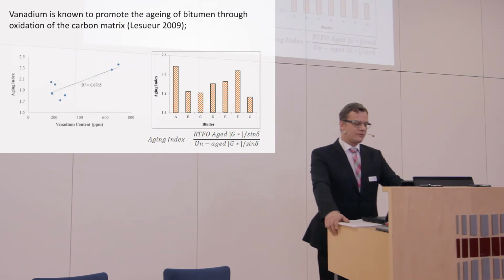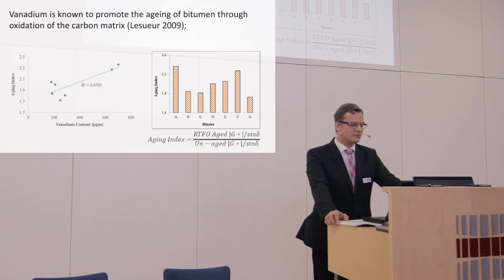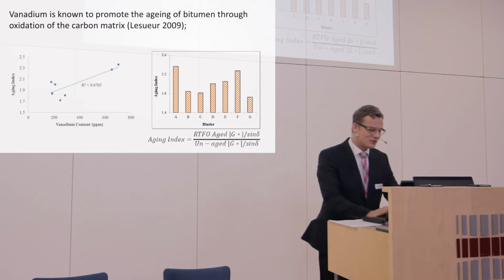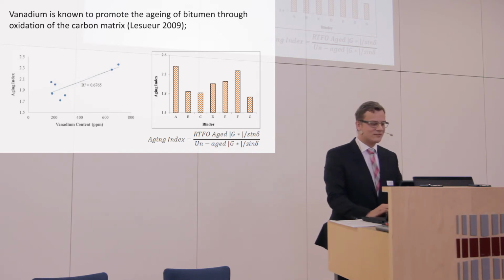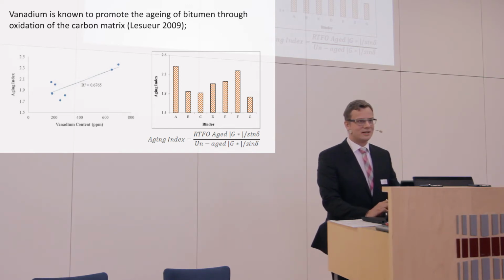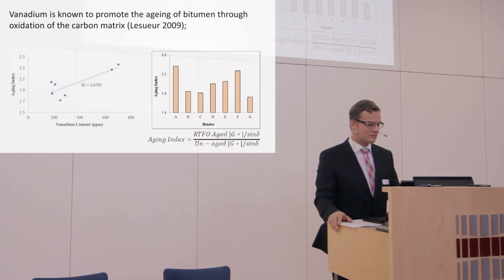Then we found out in the literature that vanadium is known to promote the aging of bitumen through oxidation of the carbon matrix. We found a little bit of correlation on this, not very strong, but still we saw that vanadium, at least in this case, could promote the aging.